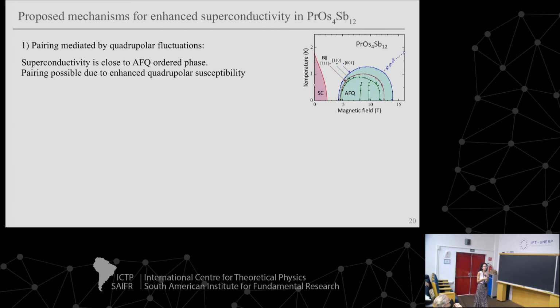So in my last one or two minutes, I told you that it's not really understood what the mechanism of superconductivity here is. But from the very beginning, a favorite candidate was that there are antiferroquadrupole fluctuations that could mediate superconductivity in a similar way to spin fluctuation mediated superconductivity in an antiferromagnetic quantum critical system. This is a common scenario in heavy fermions. You have, say, a Néel temperature that's suppressed, and then superconductivity appears near the antiferromagnetic quantum critical point, and the understanding is that the superconductivity is mediated by spin fluctuations.